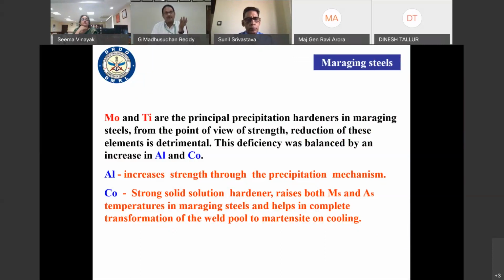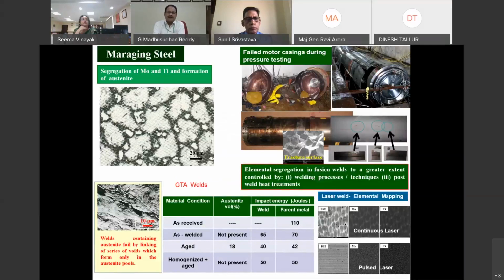But even though the problem persists, we're able to minimize the formation of retained austenite, and we are able to control the elemental segregation by changing the process. For example, if you go for laser, pulse laser, there is no segregation of moly and titanium because of the fast cooling rates. Even if you're using the TIG welding process, after welding is over, you have to homogenize it, then go for aging, and that is very difficult in actual applications because most of the things involve components. So we cannot use this kind of a treatment.